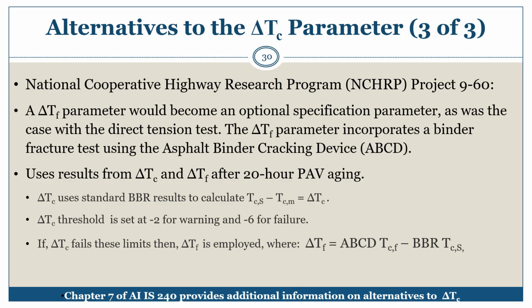Recent work by the Western Research Institute, WRI, under NCHRP Project 9-60 builds on previous research to address durability and cracking issues related to asphalt binders. A delta TF parameter was proposed by the Project 9-60 researchers as the asphalt binder property relating most closely to durability. The delta TF parameter incorporates a binder fracture test using the asphalt binder cracking device, ABCD. This uses results from delta TC and delta TF after 20 hours of PAV aging.